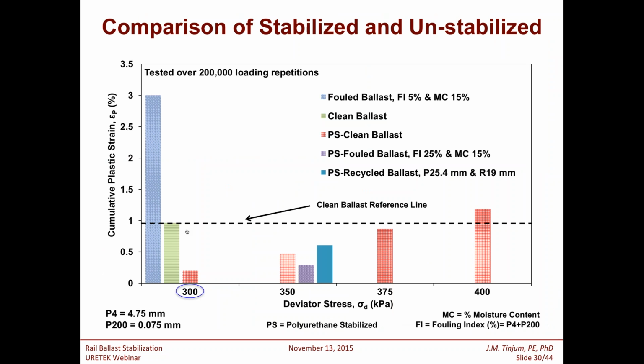outcome of this. Ultimately, in a rail substructure system, what we are interested in is how much deformation has occurred through a representative section, and we measure that as the cumulative plastic strain. Now, the FRA generally recommends maintenance at some level. I believe it's 2.5%. I might be wrong right there, but going to go through this for perspective. This is all for specimens that were tested for 200,000 loading repetitions.